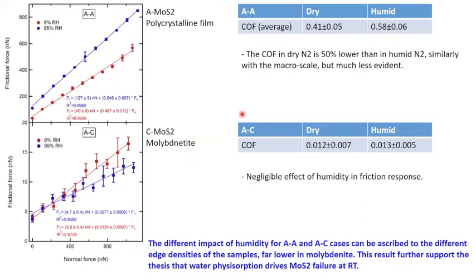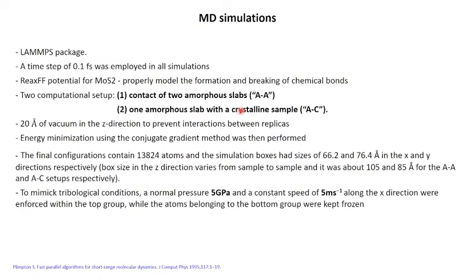In order to better understand the physical mechanism, we also performed an MD simulation thanks to the collaboration with the group of Professor Polzar at the University of Prague. I'm not really an expert in molecular dynamics simulation, so I don't want to enter too much into details. I just want to highlight that MD simulation has been done using the contact of two amorphous slabs in the case of amorphous coupling, and an amorphous slab versus a crystalline sample in the case of amorphous crystal coupling. The pressure that has been applied was 5 gigapascal, and the velocity was 5 meters per second.